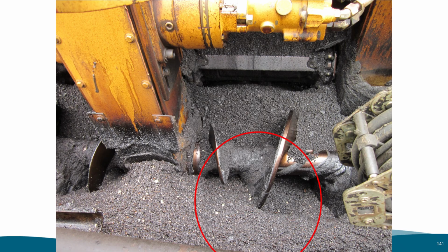This picture shows the signs of wear on the auger. The angularity of the aggregates in the asphalt can create wear on the equipment components. When the augers are worn down, it can cause segregation and uneven distribution over the roadway width. This is something to watch for during laydown to be sure that the asphalt is reaching the outer limits of the screed.